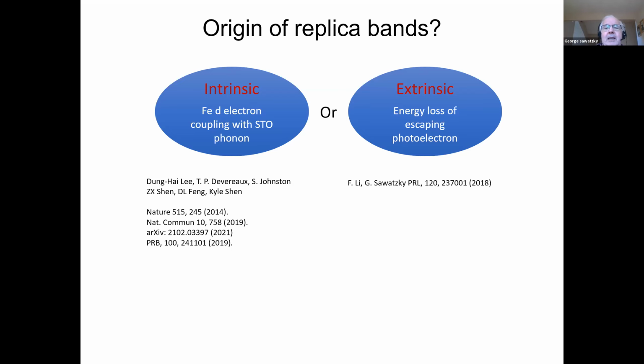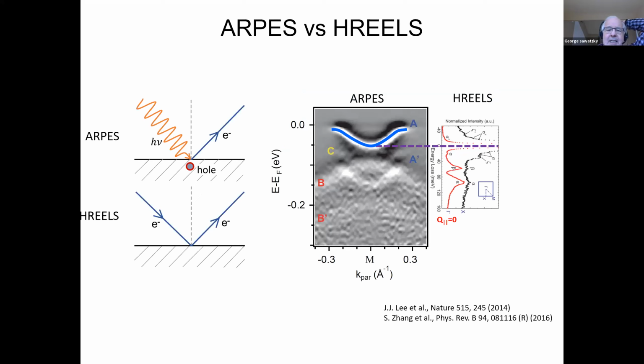Okay, very important. But it could also be that the electron on its way out is actually exciting phonons. This is very common in photoemission results, where you can have plasmon satellites, for example, coming in as shake-off peaks, as people call them, and they could be extrinsic or intrinsic, caused by either the fact that you have removed an electron from the iron and have a hole propagating there, or the fact that the electron going out is actually exciting the phonons. And I just want to show, on the left-hand side here, these two different types of things that could be happening.